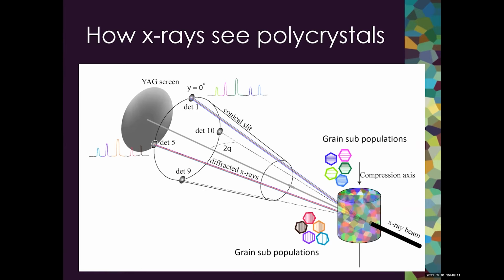So digging a little more into what's actually going on in the diffraction and what's making up this diffraction signal. Here we have our sample. This is just a simplified schematic, but we're looking at grains that are oriented with their lattice planes perpendicular to compression. And these grains are being collected by detectors along the compression direction, so detectors 1 and 9 here. And we're also looking at planes in the transverse direction where we have those planes aligned along the compression direction. Those are being collected by detector 5.